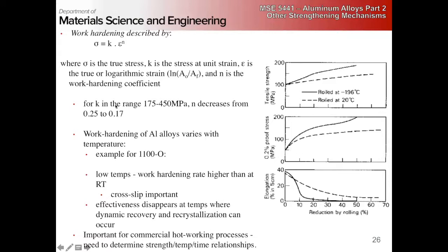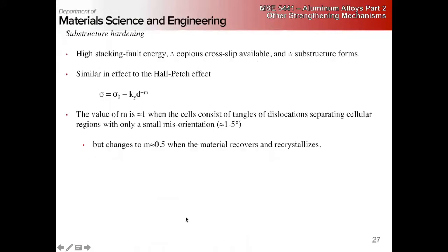And whenever we're thinking about forming, we really have to think about what our temperature is that we're going to be working at, because it's going to be a trade-off between strengthening and hardening rates versus workability due to recovery and recrystallization at higher temperatures.